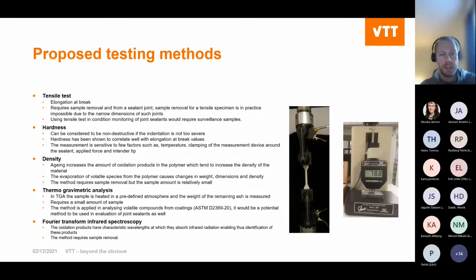Then we have gravimetric analysis. In TGA, basically the sample is heated in a predetermined atmosphere, and the weight of the sample is measured simultaneously. And it is a good method since it also requires only a small amount of sample. It has been previously used for analyzing volatile compounds from coatings, and a standardized method already exists for this. So that's why we found this method to be interesting in joint sealant studies as well.